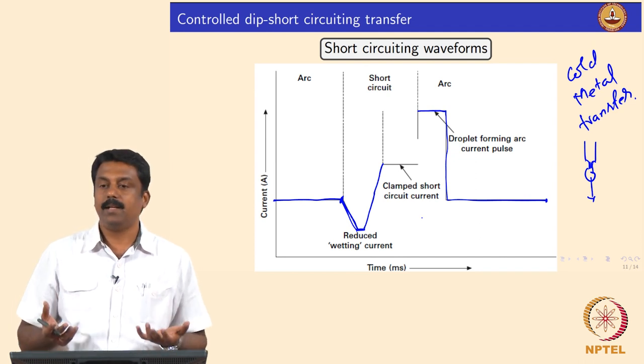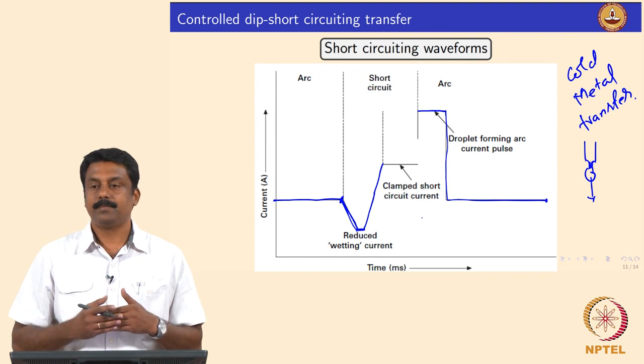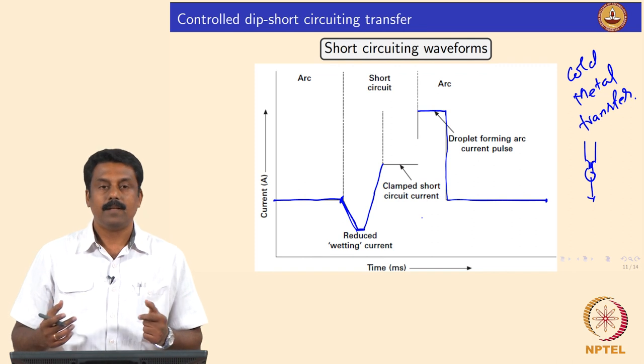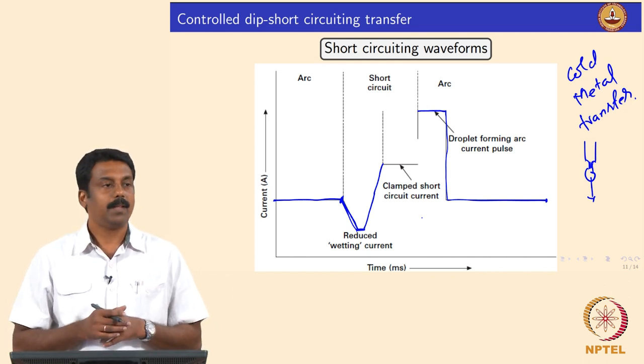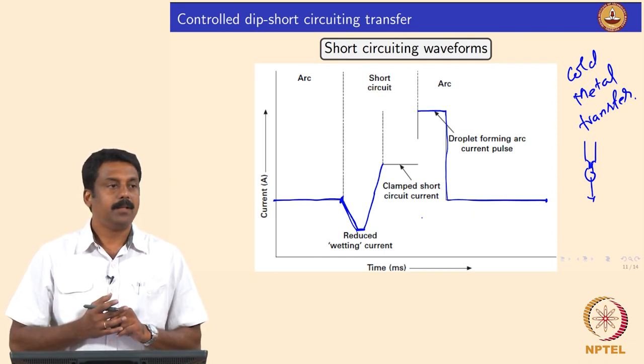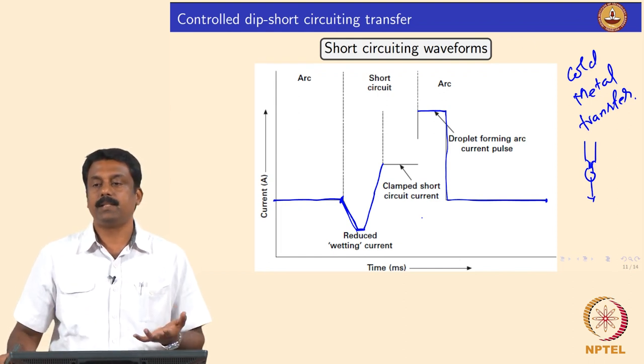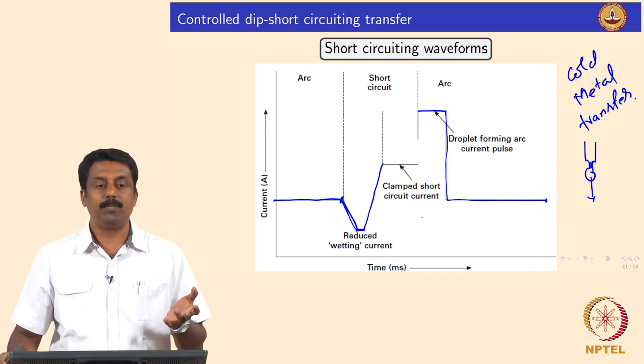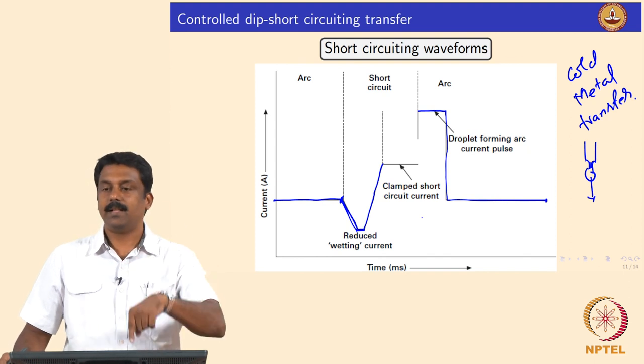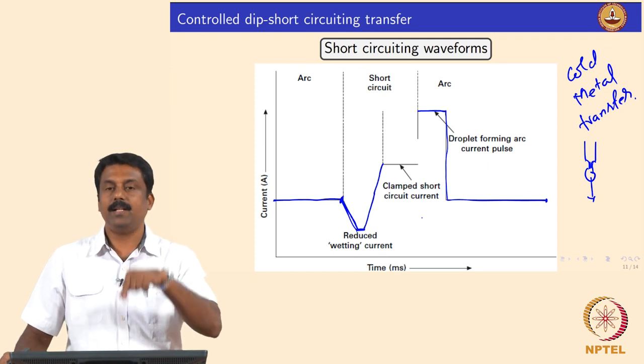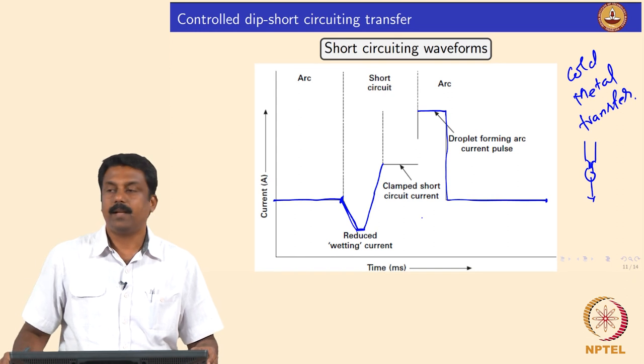This has a very high advantage in terms of heat input. If you take the average mean current of this circuit it will be much lower than in pulsed GMAW, and the droplet is transferred without any arc so you are not superheating the weld pool or the heat-affected zone. You can therefore avoid various detrimental metallurgical reactions caused by superheating — for example, to avoid intermetallic formation in dissimilar welds such as iron-aluminium, you must minimize heat to prevent diffusion of alloying elements. In those applications this process is extremely suitable. You can also achieve similar productivity because every short-circuiting event transfers one droplet, and you can adjust retraction and forward motion of the electrode to control the number of droplets transferred per cycle.